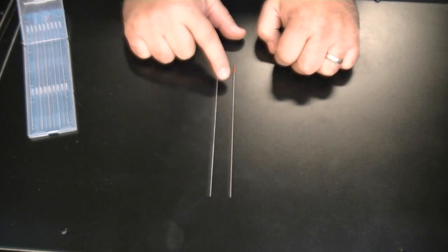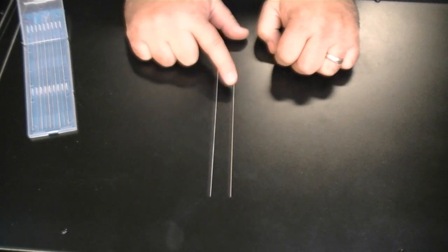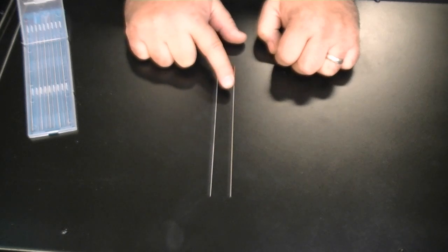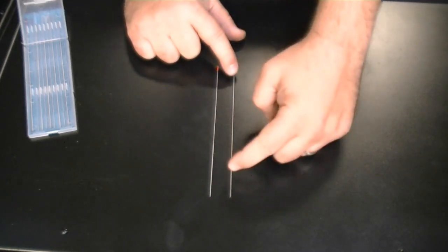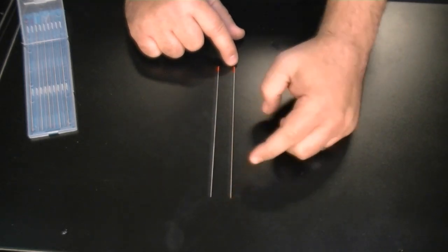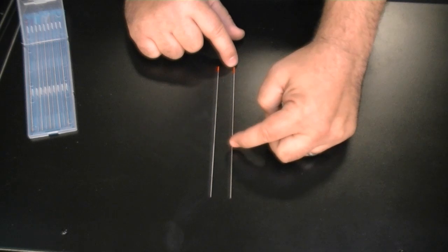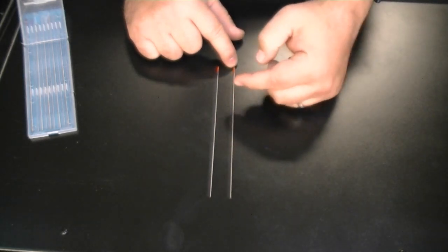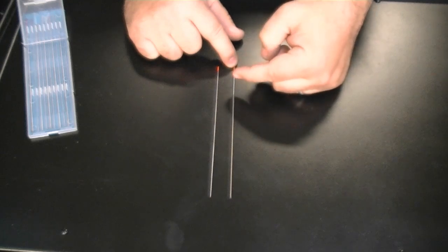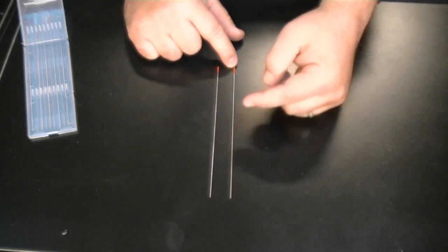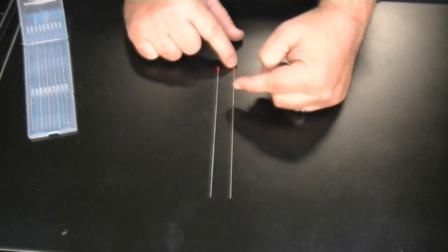If you need to go down to 20 amps or lower, or even up to 70 or 80 amps, 1/16th will work fine for you. The dangers of putting too much amperage on any tungsten is that you'll eventually lose the tip very rapidly. Not only are there multiple sizes in diameter of the tungsten, but you also have multiple lengths. This is what we call a 7 inch tungsten, and you have a 5 inch tungsten. You can break this tungsten into any length that you need, especially for TIG torches with short back caps or medium back caps.